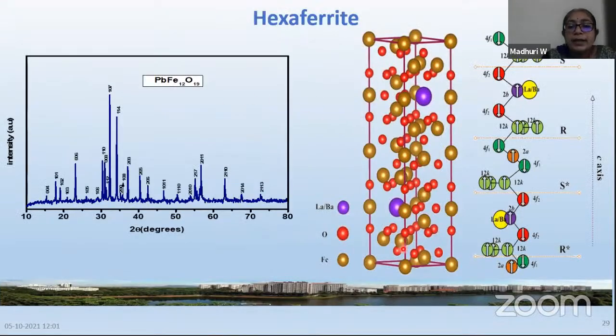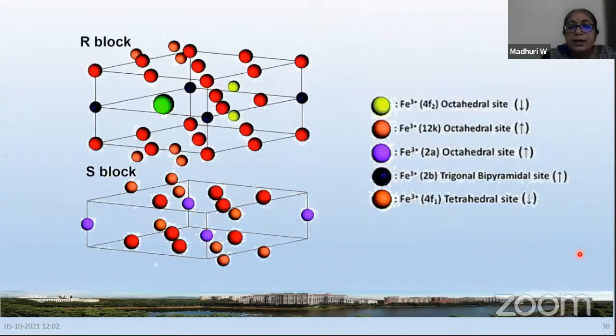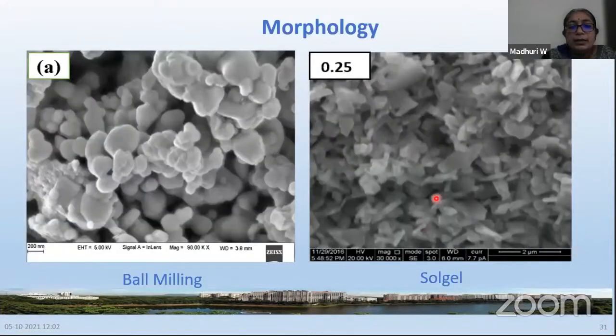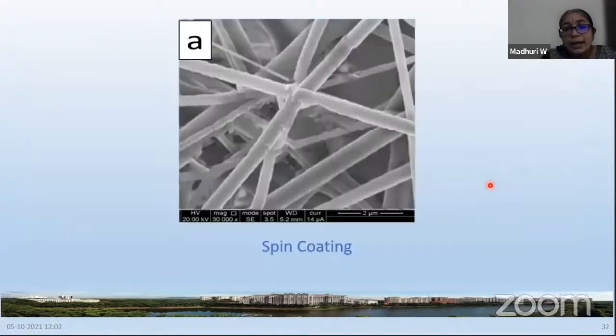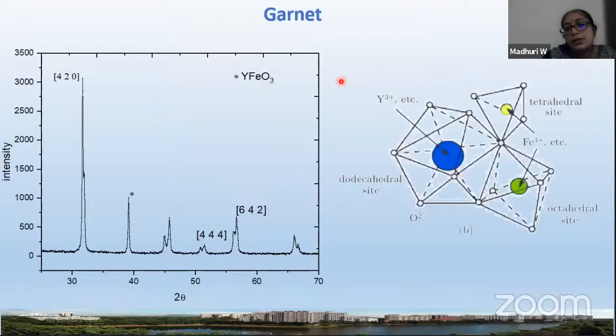Now, this is a hexaferrite, which will have a hexagonal structure like this. Not getting deep into that. And these hexagonal ferrites are being made by the solid state reaction. You see the grains are very large here using ball milling and solid state reaction, whereas by the Sol-Gel technique it is this, and by spin coating or electrospinning, you get fibers like this. You get these long fibers. You can see here, this is 2 micrometer, and the fiber diameter is much less than that. It's less than 1 micrometer. So these are nanofibers which we can develop using those techniques.